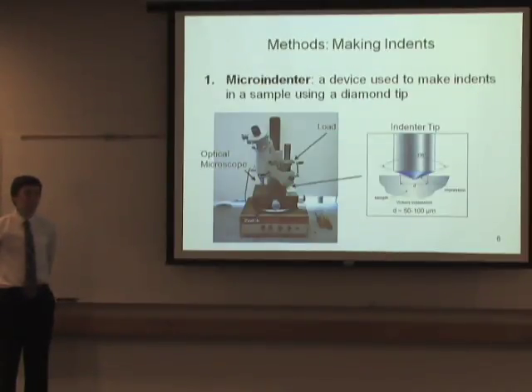And how I've been measuring the hardness is by using a device called a microindenter, which will make indents in a sample using a diamond tip. Here is the microindenter that I used throughout my project, with an optical microscope on the left, the load control just up here, and the indenter hiding beneath its container. And in order to make indents, all you need to do is focus your sample under the optical microscope, swivel the indenter over on top of the sample, and release the lever until an impression is made in your sample.